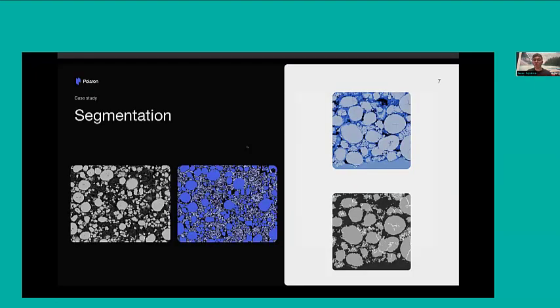And here are some of the outputs of our segmentation model. And we can see here two slightly different tasks. And in both of these tasks, we've got complex microstructures with features that are not easy to extract in an automated way. So on the right-hand side here, you can see the cracks in the microstructure being labeled differently to the particles and differently to the background or the pore phase.